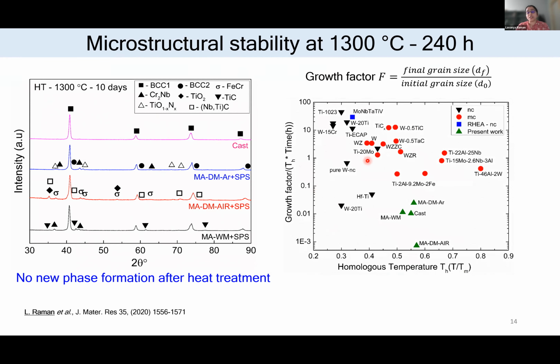When we say thermal stability, we have to make sure that the alloys have proper grain growth resistance. So for that, we calculate this growth factor, which is nothing but the ratio of final grain size to initial grain size. When I say final grain size for the powder metallurgy route, it is the grain size of the alloy after heat treatment. The initial grain size is the as-sintered grain size. So we normalized this with our temperature and time, and this is the homologous scale.